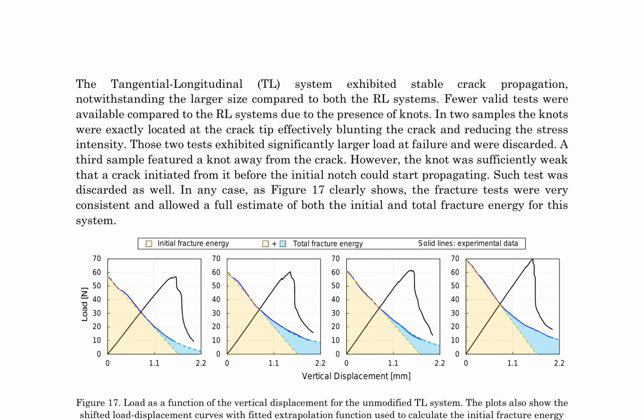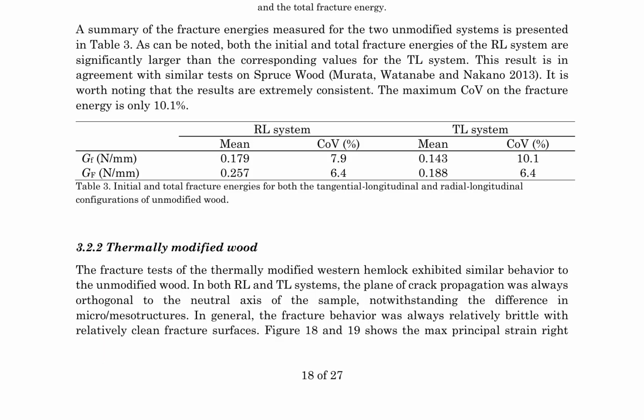The results are summarized in Table 3, which presents a comparison of the fracture energies measured for the 2 unmodified systems. The RL system exhibited significantly larger initial and total fracture energies compared to the TL system, consistent with similar tests on spruce wood, Murata, Watanabe and Nakano 2013. Notably, the results showed high consistency, with a maximum coefficient of variation, COV, of 10.1%. The fracture energies for the unmodified wood systems are presented in Table 3.